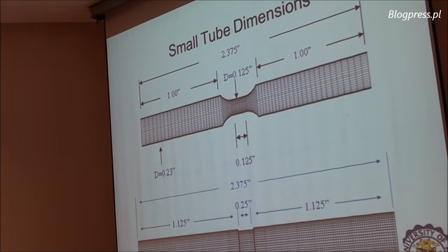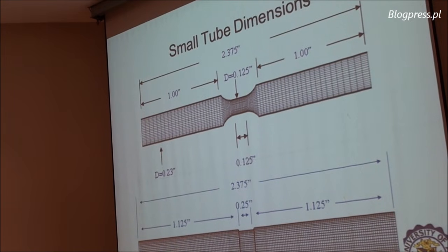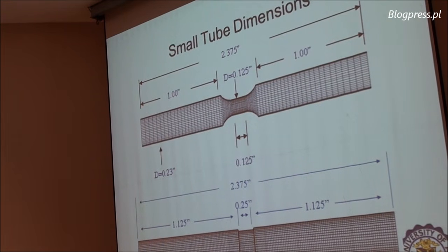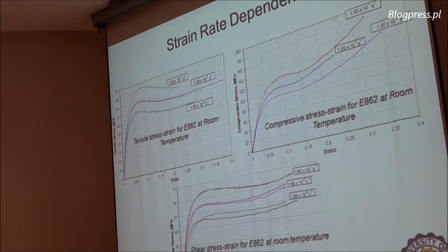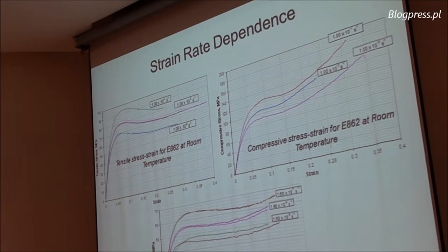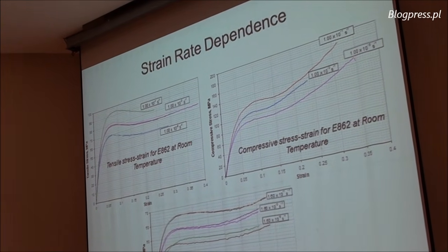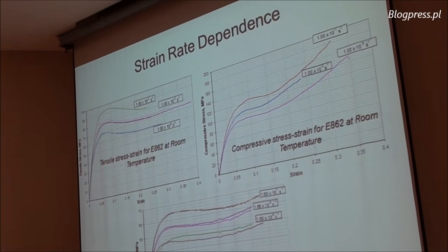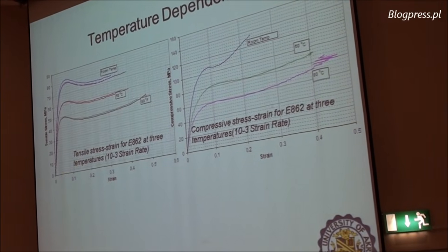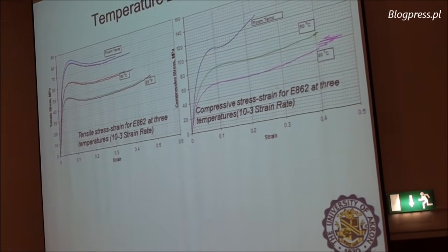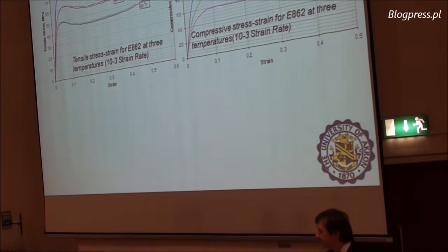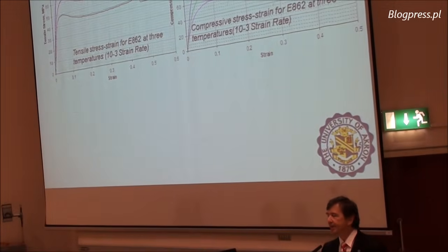The small tube shown here is of course for the torsion, and below is empty inside, and the tube of that kind can be used for the static test as well for the Hopkinson bar test for the high strain rate. So you can see the results of the strain rate testing, that the higher the rate of deformation, the different stress-strain relationship you can get. And it is basically elastic and plastic material. You can get as high as 50% strain for the resin itself.